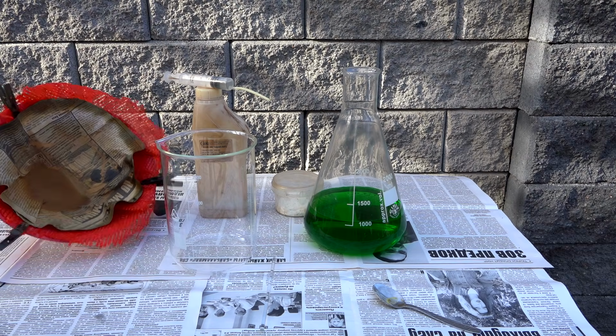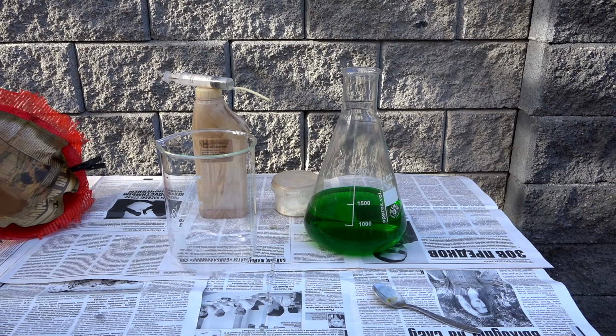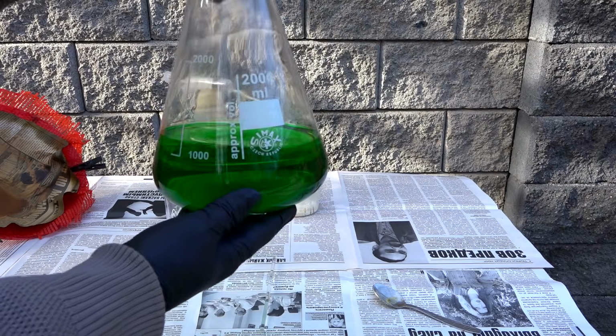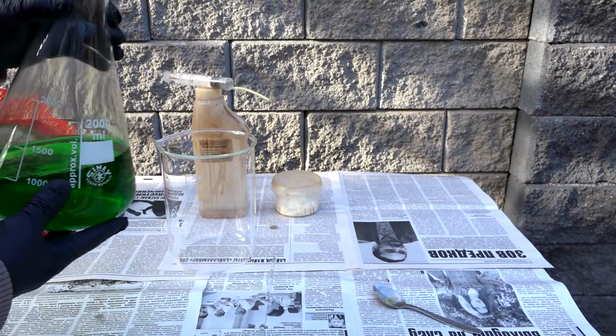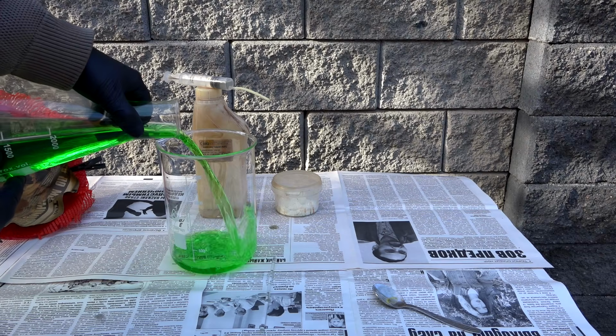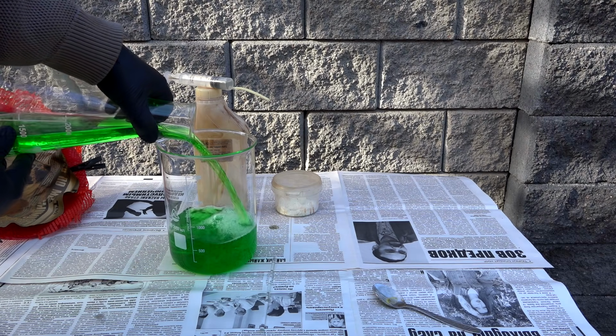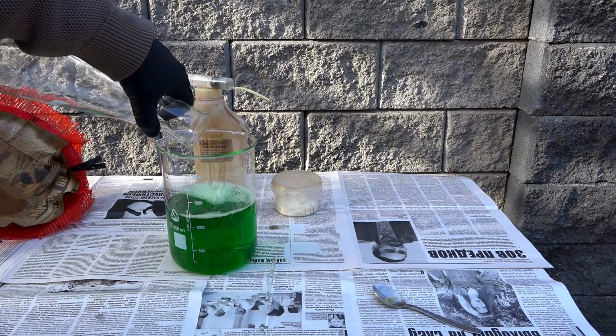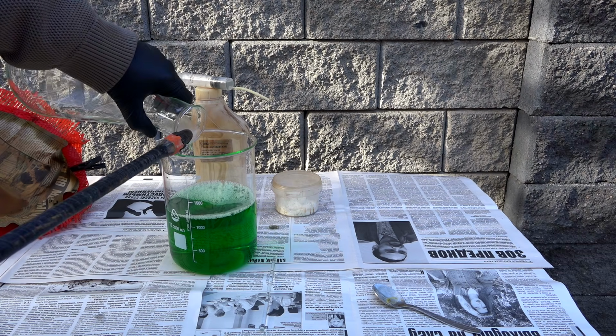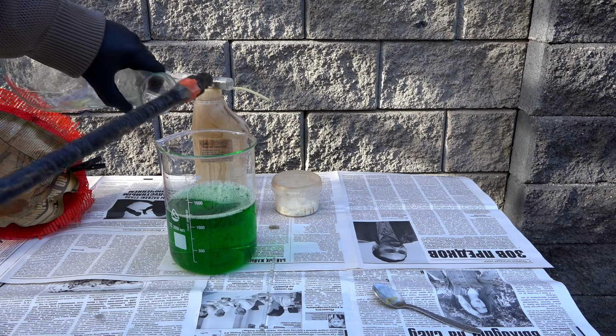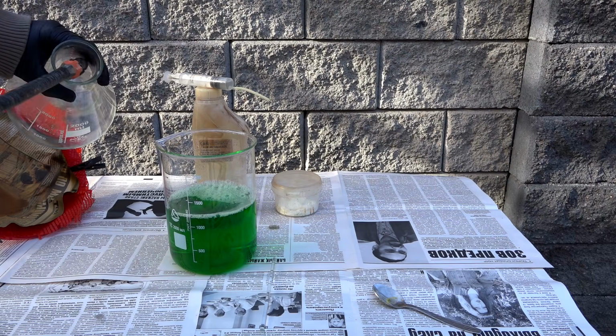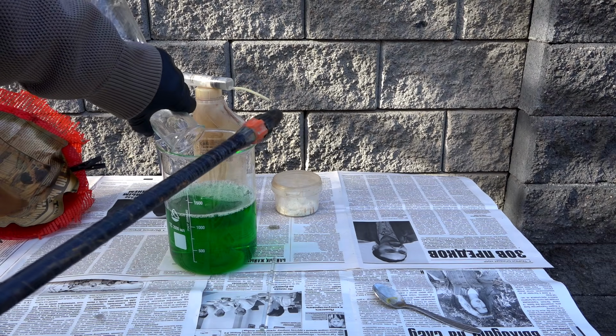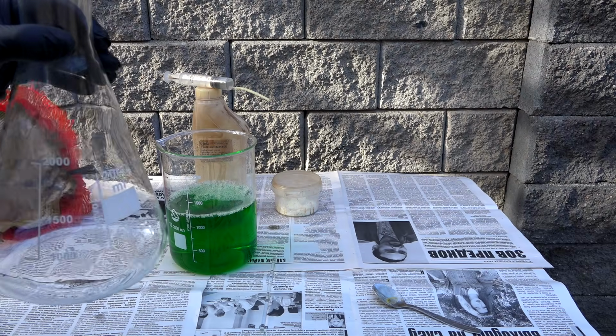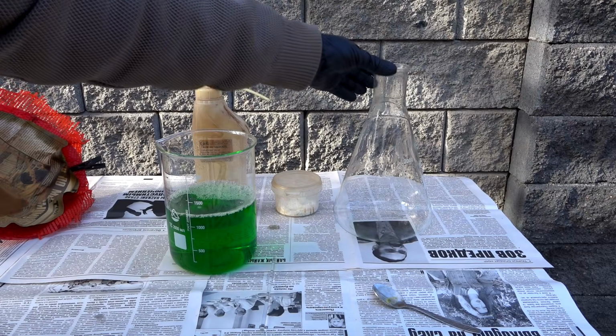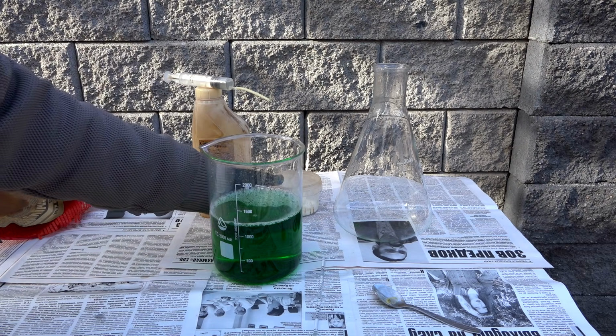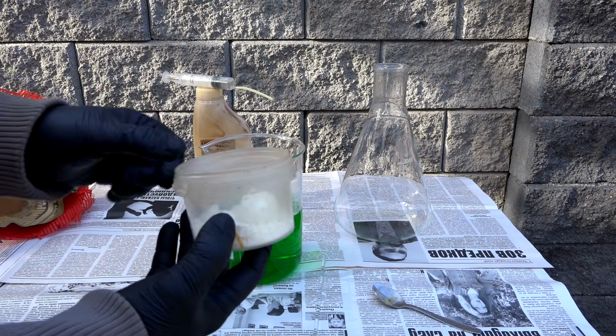Several days passed, and during this time, I obtained this clear solution, which I'll now pour into a chemistry beaker. To extract pure gold, I'll use stannous chloride and hydrazine hydrate.